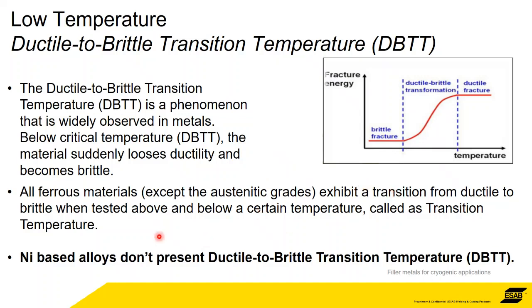However, nickel, because of the way that, on a microscopic scale, nickel is made up, nickel-based alloys don't present this transition temperature. This is the reason why. In previous talks, I've gone into detail on the composition of nickel alloys and the reasons why they exhibit the mechanical properties that they do. So based on their composition, the way that they're made, they don't exhibit this ductile to brittle transition temperature. That's why they're used.